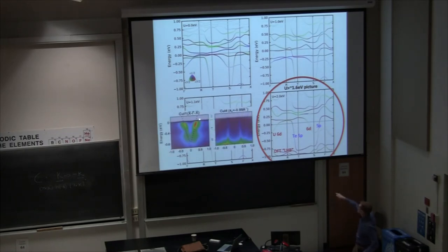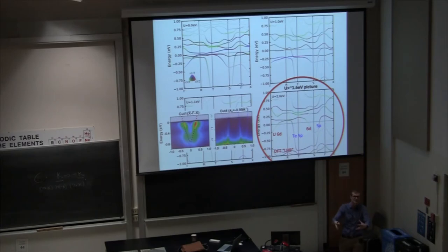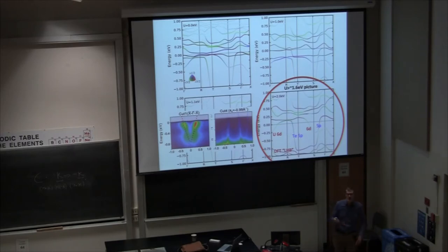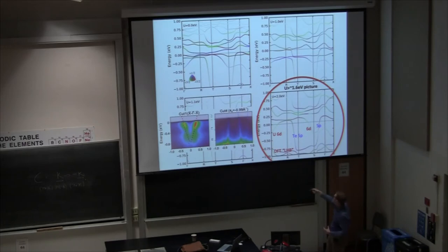It's going to turn out to be this one. If we do the measurement, aligning the instrument so that we see energy and momentum — this is actually a direct mapping from a CCD image — we get this picture. This is a band; it's parabolic up, so it's like a massive particle. And this one shooting down is a much more sloped state. So we see these states, and when ARPES works well, it gives you a simple picture. As long as you know what region corresponds to what region of momentum space, you can verify the band structure.